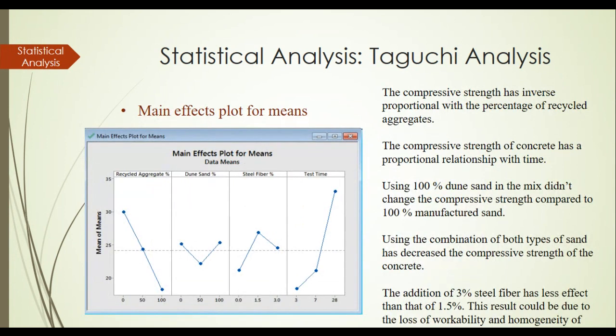And also, if we give a close look at the effect of the factors on the mean of the strength, we see very similar results to what we have seen in the factorial analysis. This also shows clearly here that the lower percentage of recycled aggregates is the better. Dune sand percentage may be a little bit different here. 50% shows worse than 0%, while 100% of dune sand is giving a good increase in the strength. The steel fiber also behaves the same. It sounds like there's an optimal here, as well as the curing time till the test time, where 28 days was showing the best among all.